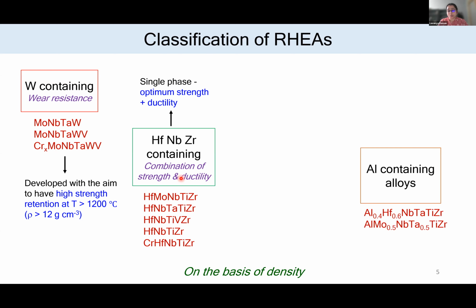And moving ahead, people tried to add aluminum to the refractory alloys, although we know aluminum doesn't have that high melting point. The main intention to add aluminum was to reduce the density and to have better oxidation resistance. These aluminum containing alloys had a B2 BCC microstructure, which is similar to the superalloys, like a basket weave microstructure. They showed optimum density, strength, and ductility. So this was a really good way of making alloys which satisfies most of the criteria.